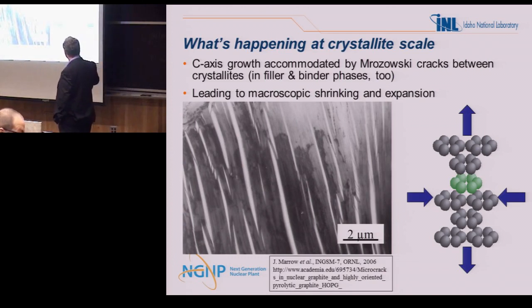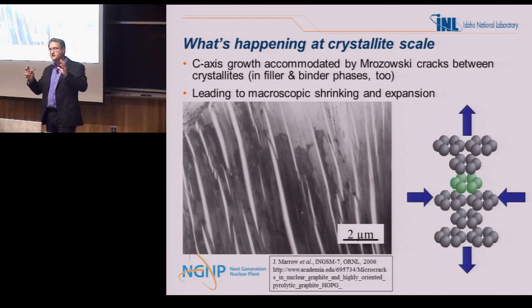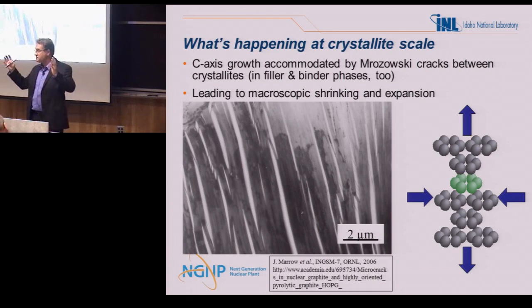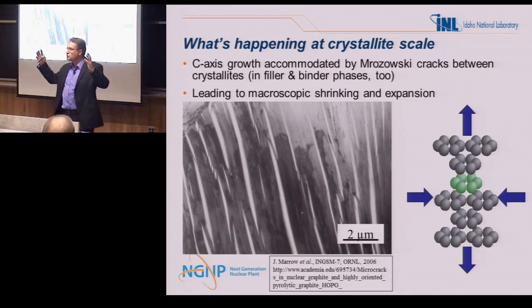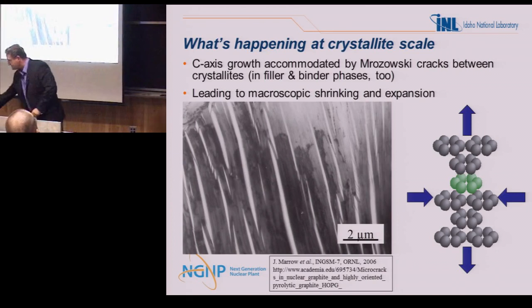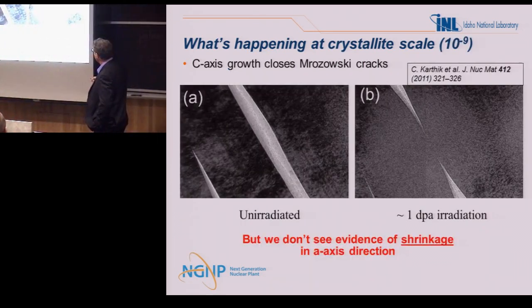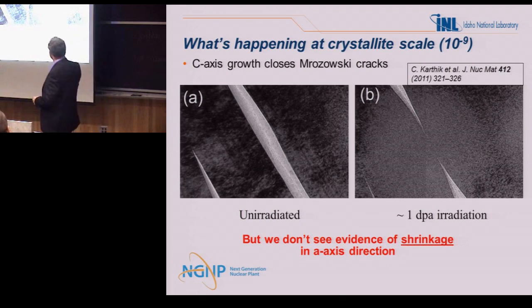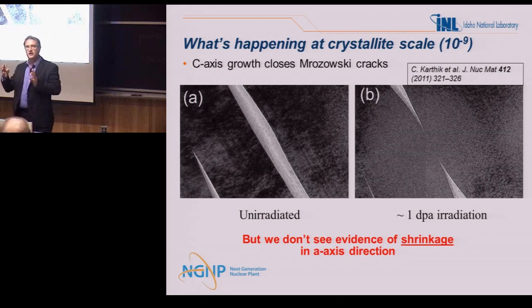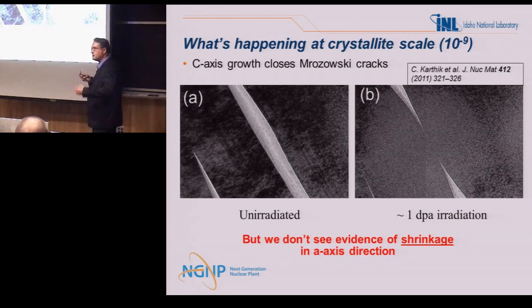So you've got this going on at the atomic level, at the crystallite level. Remember I talked with you about the fact that this graphite is processed at 3,000 degrees Celsius. Well, the thermal expansion is much greater in the C direction because of the weak bonding. So it swells. During cooling, when everything is rigid and brittle, it starts to contract, and as it contracts, it literally opens up into what we call Mrozowski cracks. So what's interesting is that under irradiation, it grows in the C direction and it closes these millions of Mrozowski cracks. And so you never see it at first. It's hidden by the fact that you've got this pre-existing crack void that it's filling up for the first part. The only thing you see is the shrinkage in the A direction.